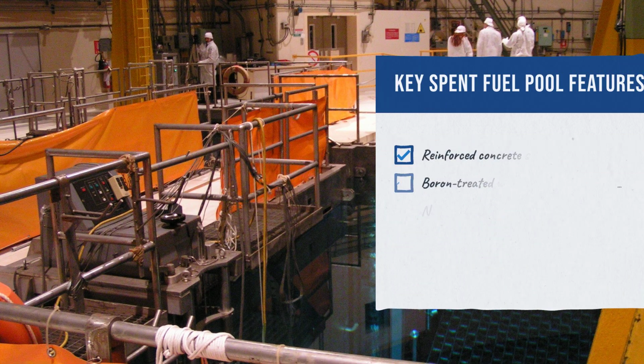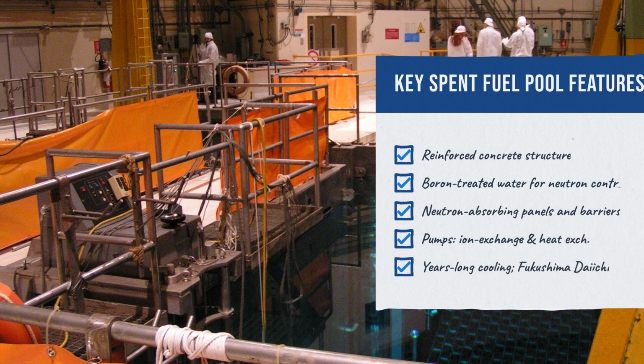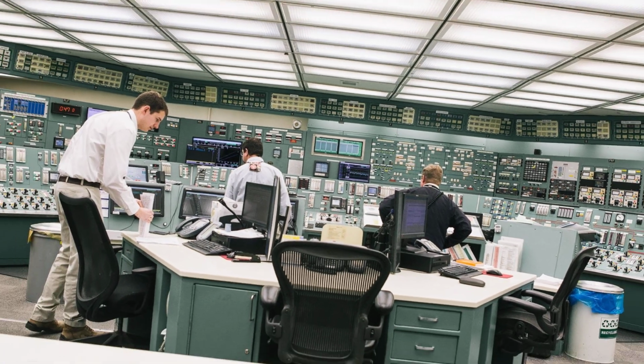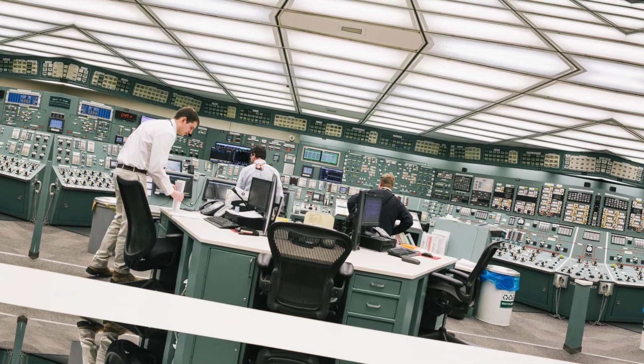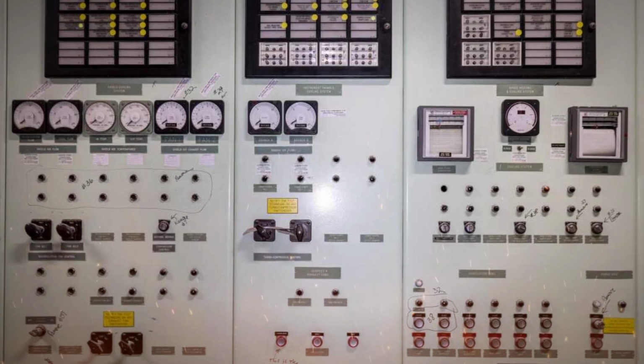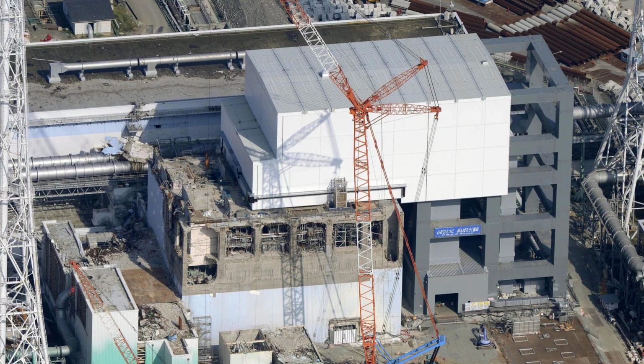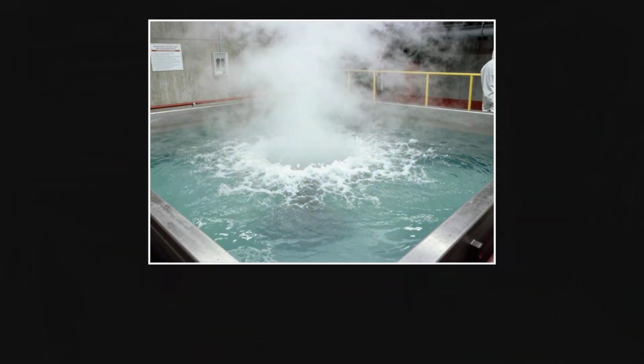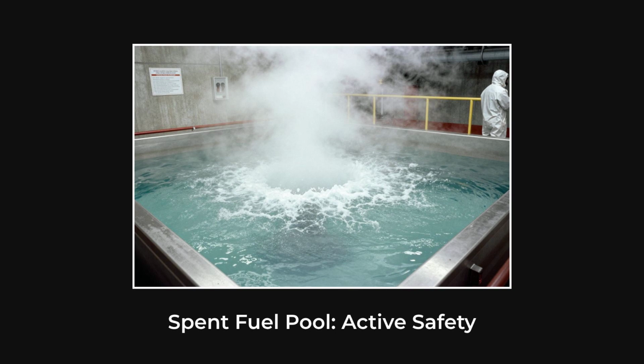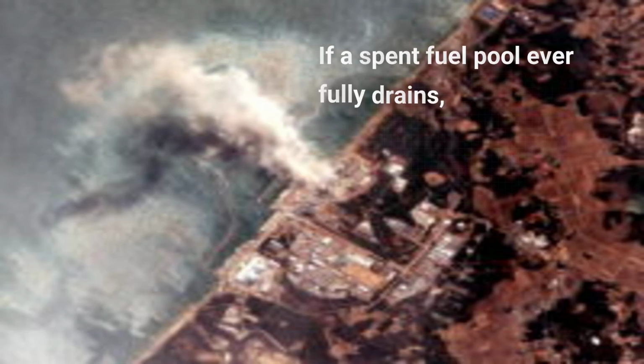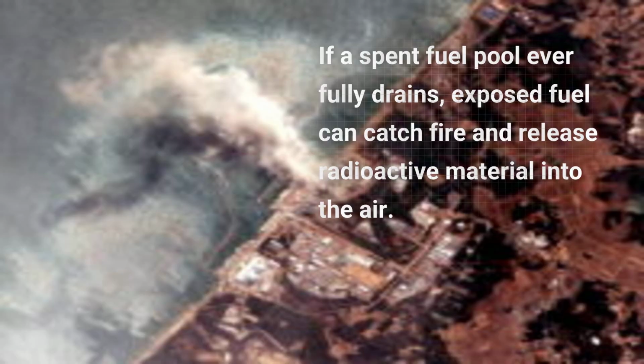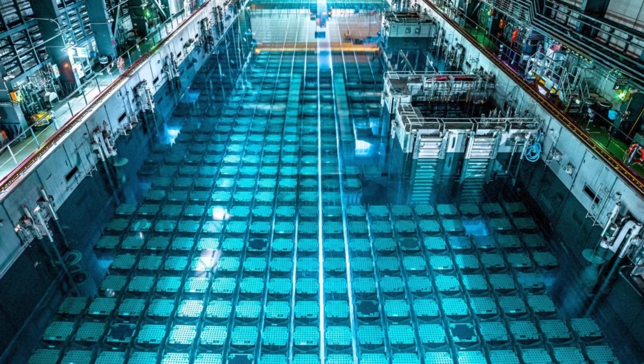Active circulation pumps move the water through ion exchange resins and heat exchangers continuously, around the clock, for years. If that cooling system ever fails, the situation becomes serious quickly. This was one of the central concerns at the Fukushima Daiichi spent fuel pools after the 2011 earthquake. A pool that loses circulation will heat up, the water will begin to boil off, and if it ever fully drains, the exposed fuel can catch fire and release radioactive material directly into the atmosphere. The pool is not just a storage container. It is an active engineering system that has to keep working.